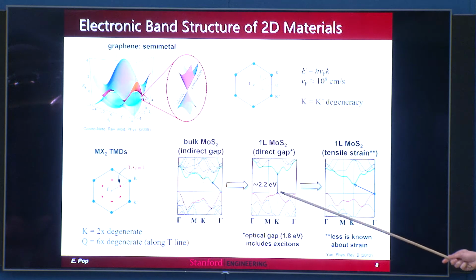The direct band gap of this material, of MoS2 in this case, is about 2 point some electron volts. You might hear the number 1.8 thrown around a lot. That's actually the optical gap of the material. There's very strong excitons in this material. So when you do a photoluminescence measurement, you get 1.8, 1.9. But the true electronic direct band gap is actually larger. And it's also a function of the dielectric environment, it turns out. I wrote approximately 2.2, but it could actually be 2.3, 2 point something.